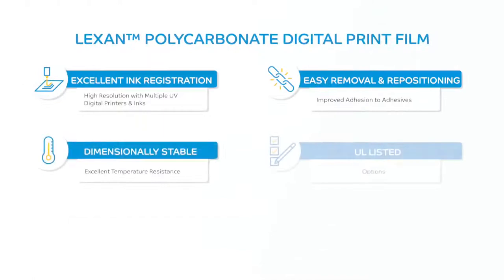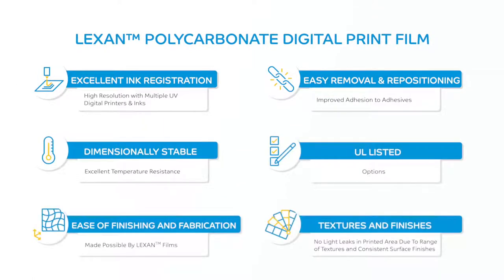It prevents UV ink delamination in adhesive label applications. These films are primed on one side and specifically designed for increased digital UV ink adhesion and are robust for permanent and temporary pressure sensitive adhesives on the printed surface.